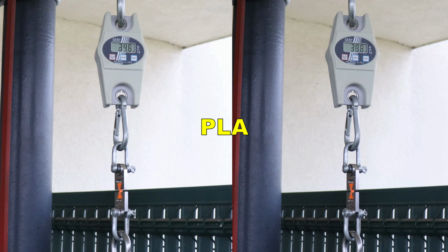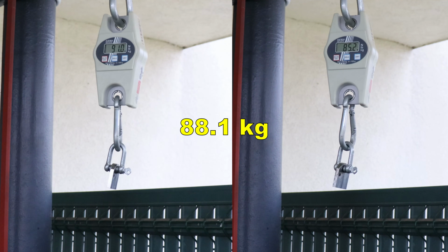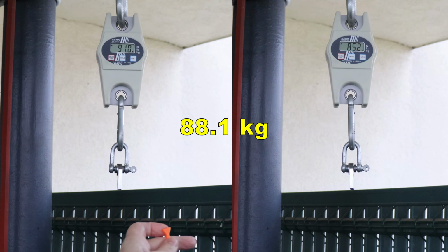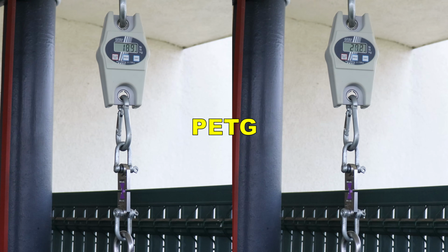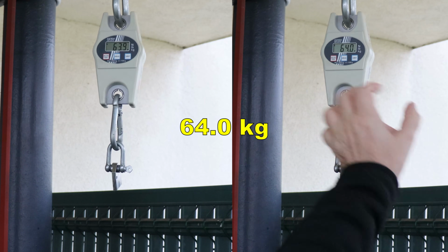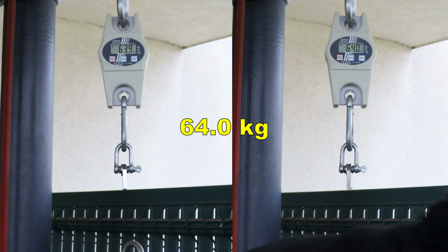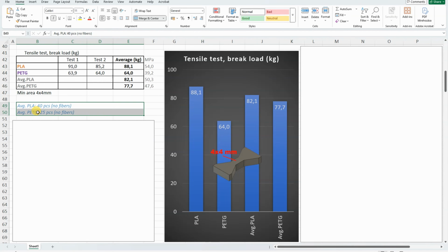Tensile test with horizontal printed objects, PLA, PETG. I already mentioned that I will include here the average PLA and PETG filaments. Now we can see the PLA compared to the PETG is noticeably stronger, and this PLA is stronger even compared to the average PLA materials. The PETG is noticeably weaker compared to the average PETG.